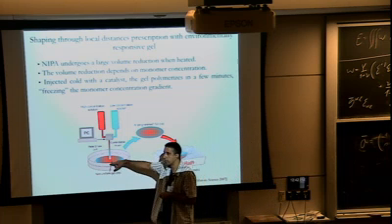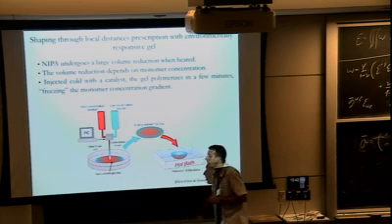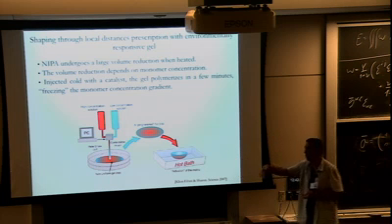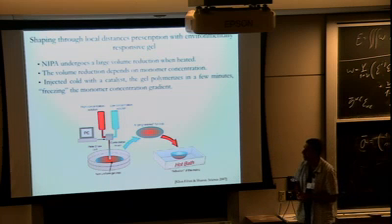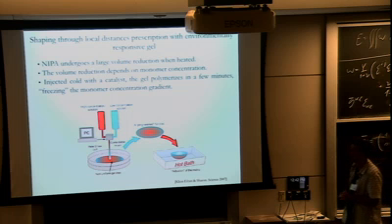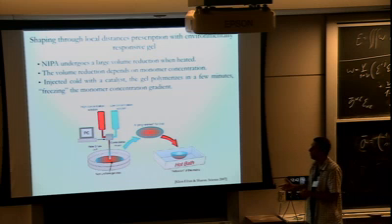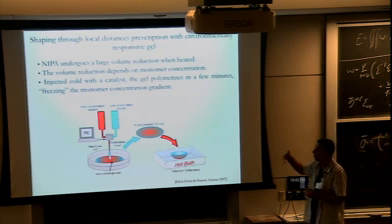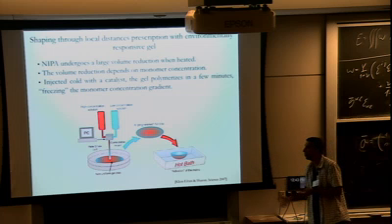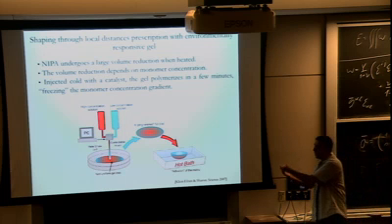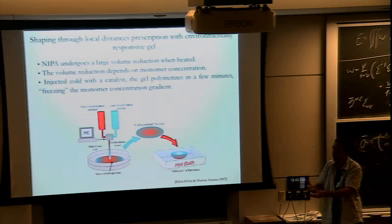Put it faster or slower into the shell? Yes. And controlling the viscosity of the fluids will matter, and controlling the polymer density would matter. Nowadays, there are more advanced systems. I just didn't have the slide in advance. You can do these things by photocross-linking. So you do this with riboflavin or some other UV photopolymerizing agent, and then you can have areas which are heavily cross-linked and dilutely cross-linked and would have the same effect.